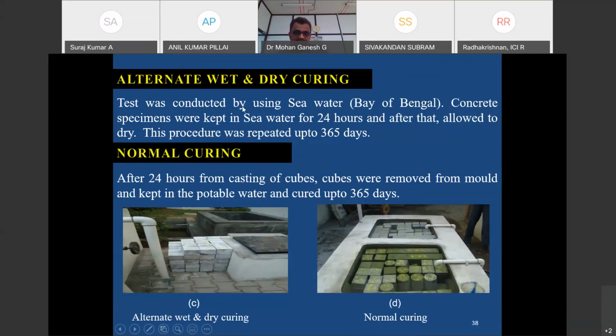So for this, we have collected the water from the Bay of Bengal, and parallelly we created a tank and we put all the specimens into the tank on alternate days. This procedure was repeated up to 365 days to check the durability. Earlier we thought of simulating the seawater, because if we simulate the seawater, we can easily maintain proper quality control. But we want to know the behavior in the actual water. So for that only, we have directly collected it from the Bay of Bengal.